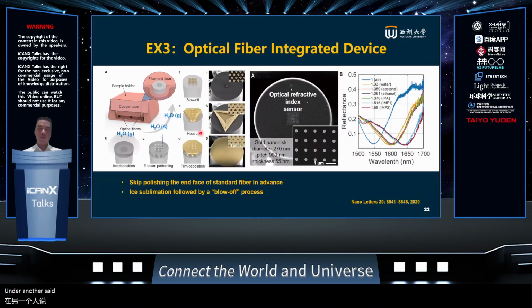Another, third example is the optical fiber integrated device. As we said, we can basically do e-beam lithography on almost any surface, as long as we can cool it down to a low temperature. Or I forgot to mention that by cold ice, I meant something around 150 Kelvin, 130 to 150 Kelvin. So this is slightly above liquid nitrogen temperature.